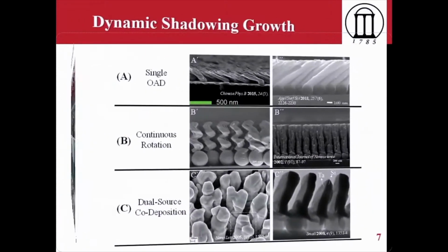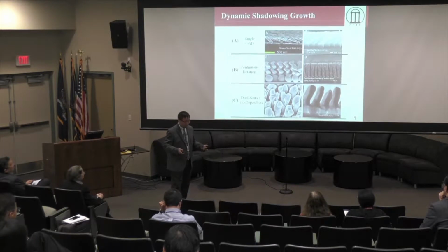Usually, when we use the colloid monolayers, we tend to use them as a template. The shadow effect has a so-called self-alignment effect. When you have the colloid monolayers, they act as the seeds, so the grown nanostructures can align on top of the seeds, and you can form a regular-spacing nanostructure this way.